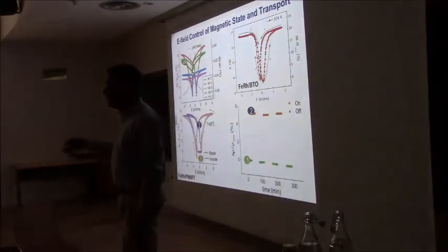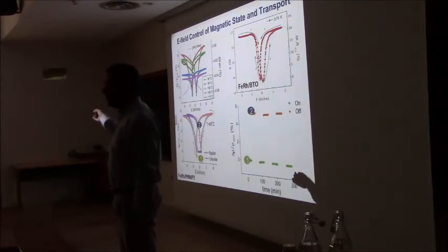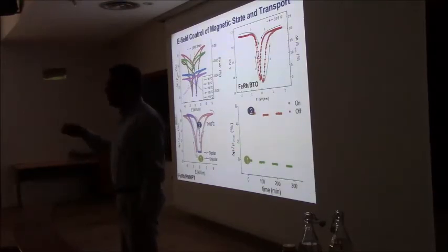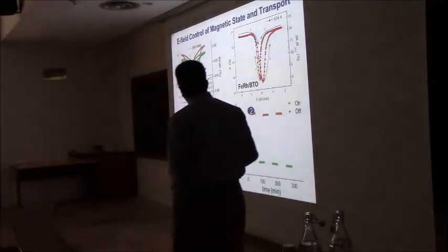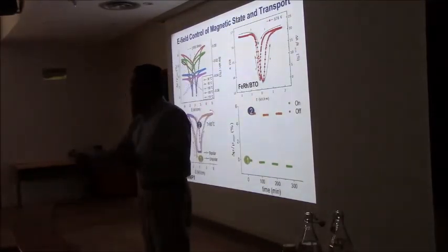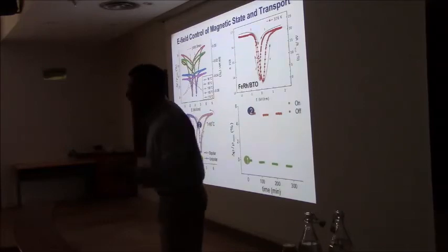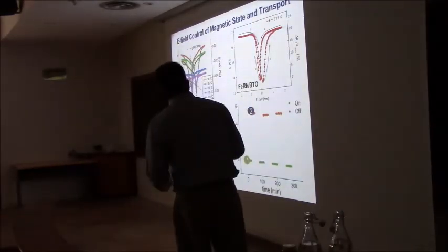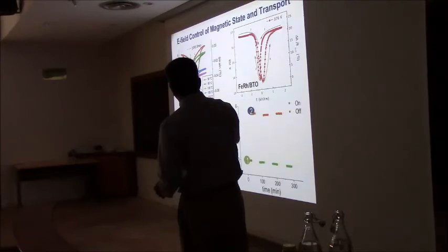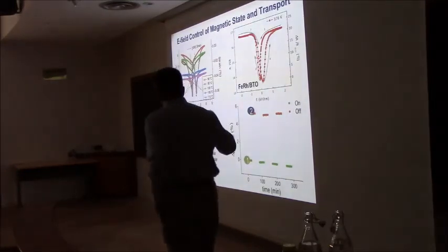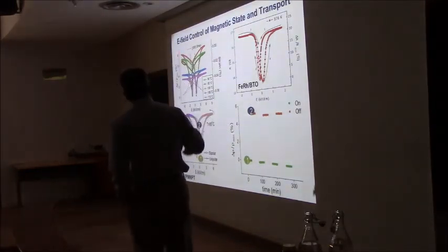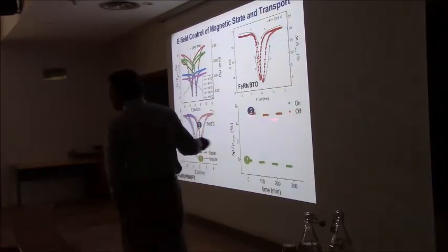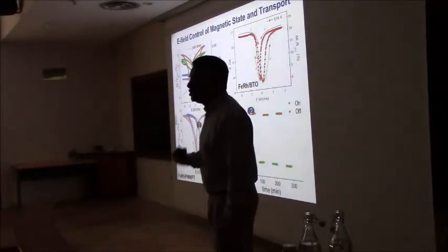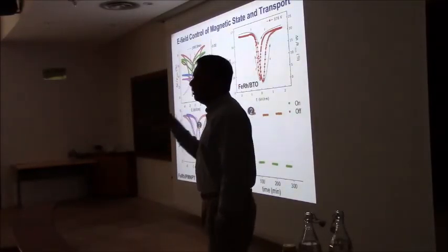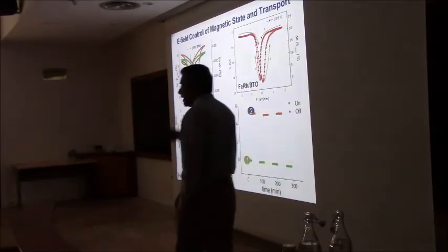You say, why did that happen? It happens because it's going from a ferromagnetic state to an antiferromagnetic state. Spin-dependent scattering is changing. You're also changing the mesoscale distribution of the ferromagnet phase and the antiferromagnetic phase. And it's just temperature dependent, because this happens right around the transition temperature of the system. You can put it into the two states, the one state and the two state. They're very stable, which says that this is indeed fundamentally changing the material from one ferromagnetic phase to an antiferromagnetic phase.